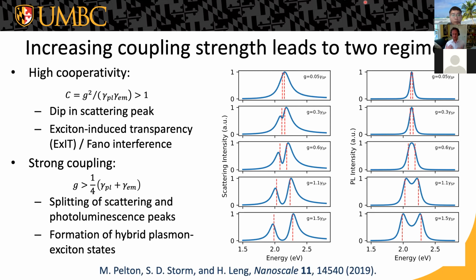Again, waving my hands, it's because of an interference between the radiation produced in a sense between the plasmon and the exciton. It's a coherent effect that shows up in scattering because scattering is a coherent process. Photoluminescence is not a coherent process, right? You excite at a certain wavelength and then it relaxes internally and then emits light. So the coherence of your driving field is lost in the photoluminescence process. So the induced transparency comes because of the coherence between the driving field and the scattered field, so you don't see it in photoluminescence. That's why I like to use photoluminescence as a sign of strong coupling. If you see splitting in photoluminescence, you know you have strong coupling. Okay, thank you. Sure.